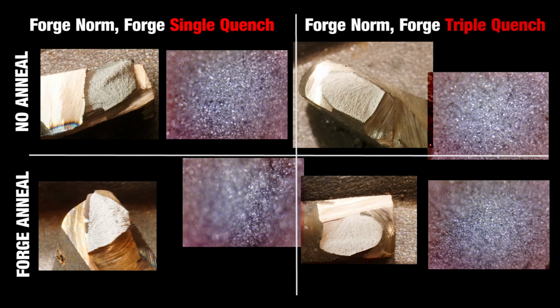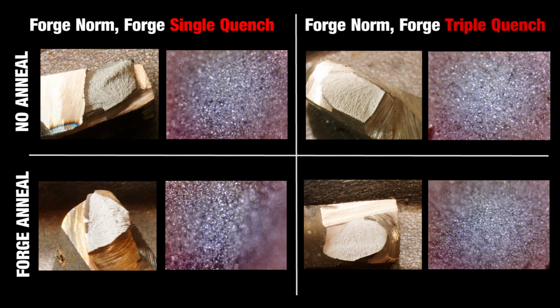As you can see, I took the single and triple quench and compared it to doing the anneal cycle first and not. The pictures on the bottom row are a little bit different. They have different lighting. There's not as much shadow, so the grains look finer there. I would sort of ignore the photos and go with the microscope pictures. Does the triple quench come on top after annealing? I don't know why it would. The single quench didn't change much. I don't know. Interesting results.